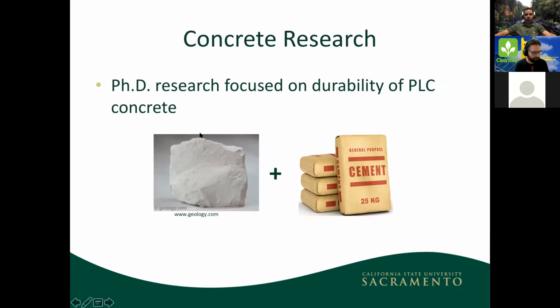And this is actually what I worked on for my PhD at the University of Texas at Austin. The Portland limestone cement basically takes some ordinary cement and combines it with limestone that is pulverized. It is ground into a very fine powder, and it is combined with the cement, usually in relatively small proportions of 5 to 15%. But my research was looking at increasing the limestone portion to as high as about 30%.